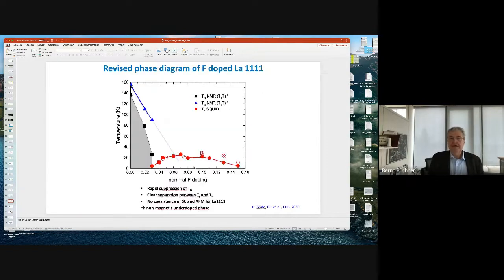Okay, this is the phase diagram which we have revised. First, we did that on polycrystalline materials. Again, fluorine doping is possible here. We see the phase diagram. We have these two phase transitions. So the nematic phase transition here, the magnetic one there. We have a decrease here of this nematic phase transition. We lose the signatures of the phase transition here. Magnetism disappears, and then superconductivity emerges. And already looking at this phase diagram, it seems that maybe superconductivity is not connected to, let's say, quantum critical behaviors of the magnet, but more connected to this nematic instability.